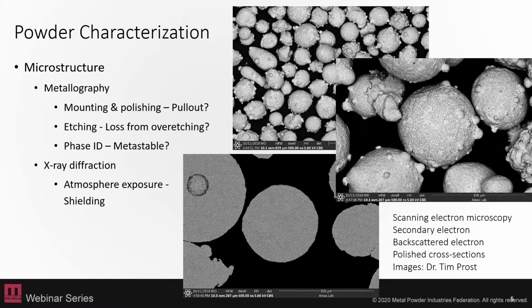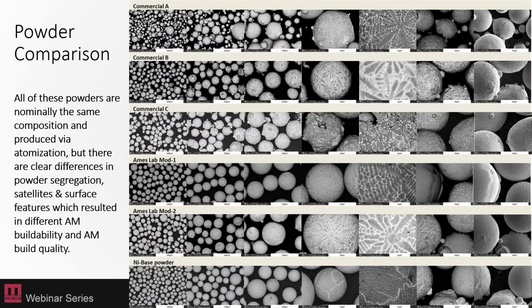Just as a comparison, this is a study that we did in-house looking at some nickel-based superalloy powders. All these powders are nominally the same composition and produced via atomization, but there are clear differences in how the powders have segregated, what the satellite features are, and what their surface features are, and all of these powders then had different AM buildability and different build quality resulted from these powders.